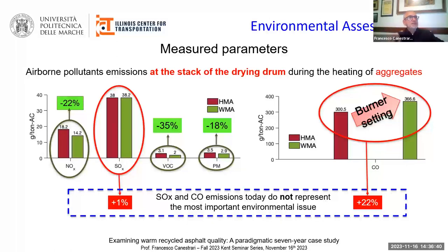First, we have to say that sulfur oxide and carbon oxide emissions do not represent the most crucial and important environmental issue. Moreover, the increase in carbon oxide emissions can be solved with a better burner setting, because when the temperature is lowered, the asphalt plant must have a different setup to achieve optimal fuel combustion.